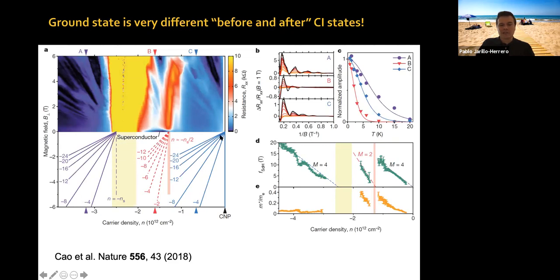We had already seen that from charge neutrality, or from the band insulator, the degeneracy of your Landau levels is fourfold. So you have this fourfold flavor symmetry. Whereas at nu equals minus two, you have twofold Landau level degeneracy. So you have broken your symmetry, and now you have two rather than fourfold symmetry. This was already present when you measured the frequency of the Shubnikov-de Haas oscillations, the effective mass of the system.